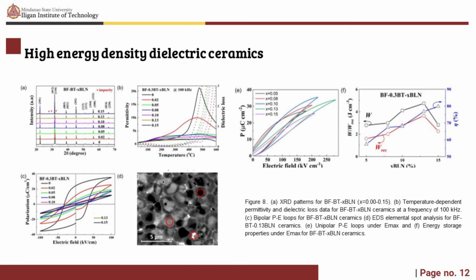The undoped BF-BT has the biggest grain size, about 8 microns. The grain size decreases significantly for BLN doped compositions, which can be seen in figures S6 and S7 in the electronic supplementary information, accompanied by the formation of a core-shell microstructure with BiFe-rich bright, Ba-rich dark, and Bi-rich bright grain boundary phase. This can be seen in figure 8d and table S2. In the electronic supplementary information, the Bi-rich bright grain boundary phase corresponds to impurity peaks in the XRD pattern.